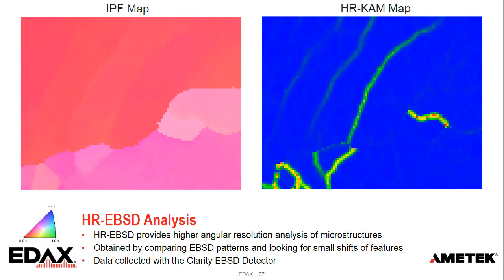And we can look at this with what we call HR-EBSD, high angular resolution EBSD. This is a technique that provides higher precision in the orientation data. It is achieved by comparing two EBSD patterns in a cross-correlation Fourier space, looking for small shifts of features within the pattern. This is in contrast to our standard Hough-based indexing. This data was collected with our Clarity direct detector to get really high quality patterns, to see how well we could measure this.